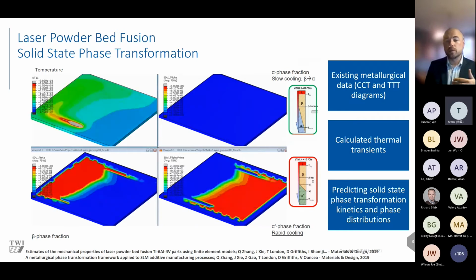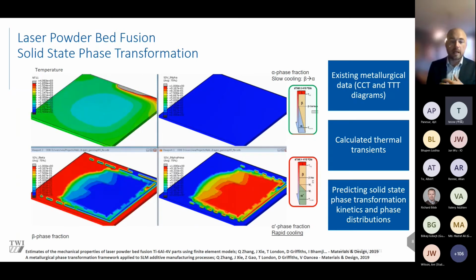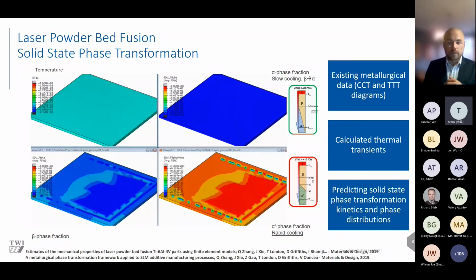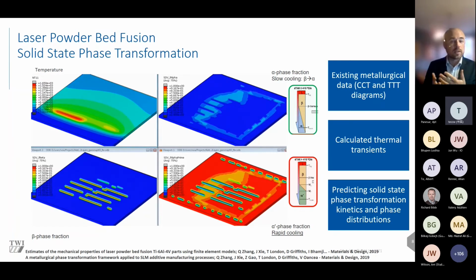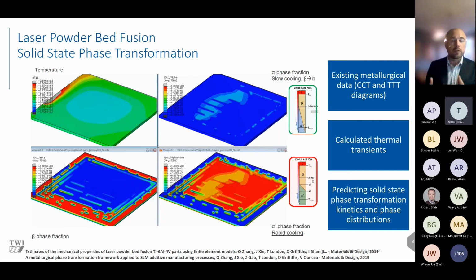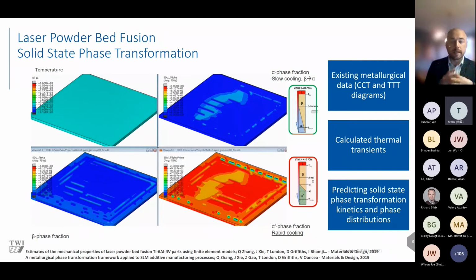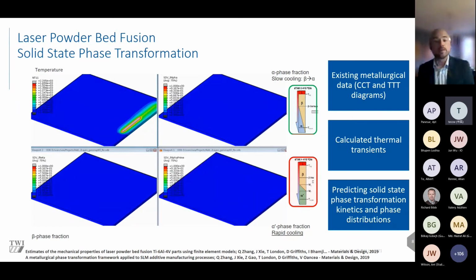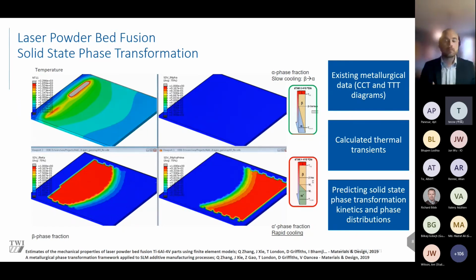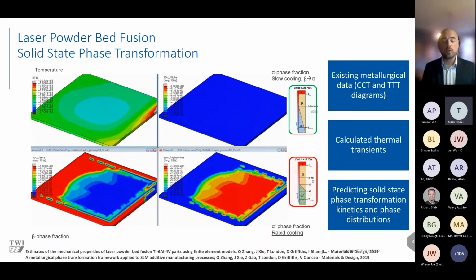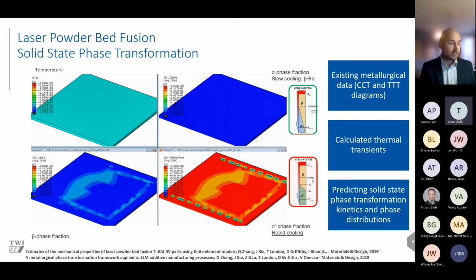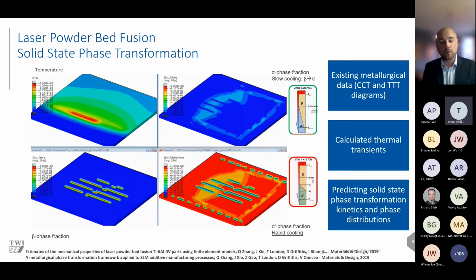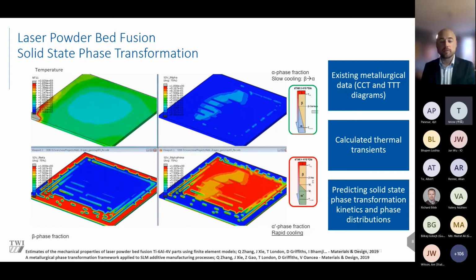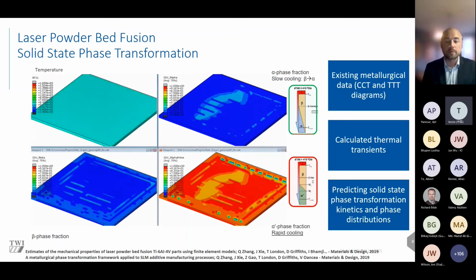With confidence in the thermal model, we can start to look at things like how the microstructure changes. Again, adapting mature capabilities from the welding engineering world, where we look at solid state phase transformations in ferrous alloys and others. We can do the same for titanium alloys, where very rapid cooling takes us from a BCC high temperature beta phase into something more acicular, where slow or more diffusive transformations can take place if we don't cool so rapidly. And ultimately, the temperature and the temperature transients determine the microstructure, and the microstructure determines the mechanical properties. So if we want to know how this is going to perform, we need to start linking all these variables together.